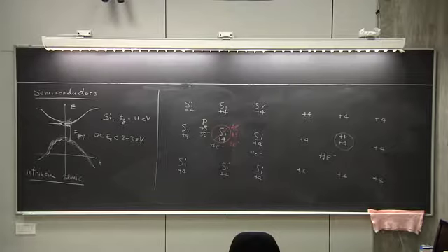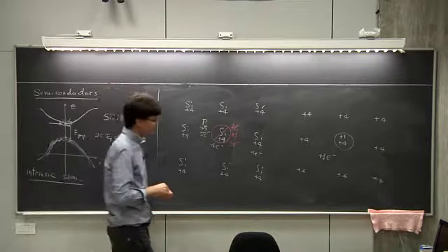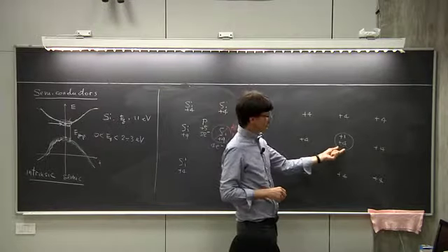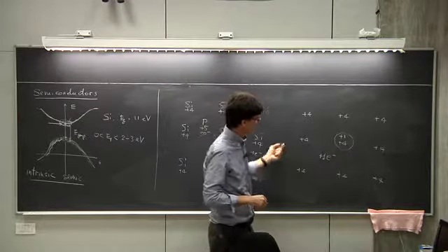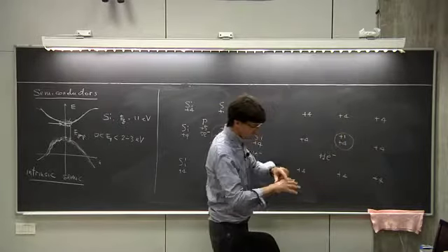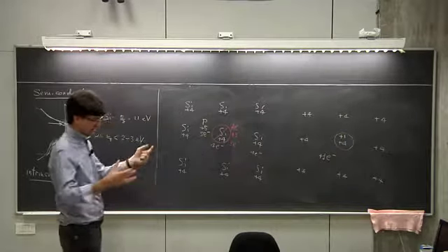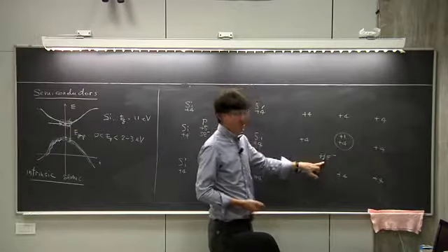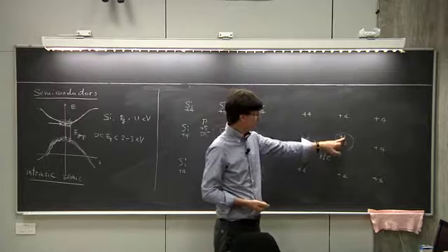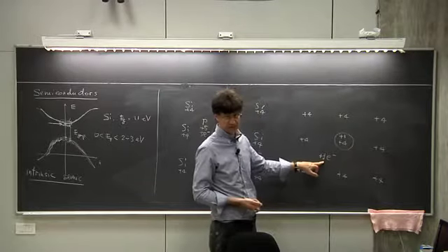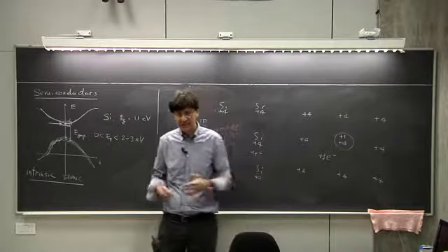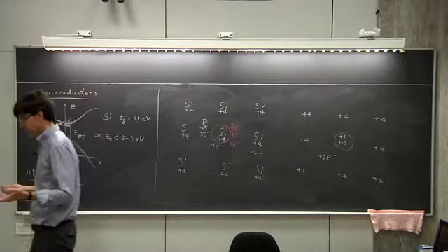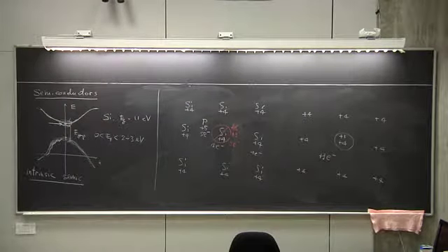In fact, without trying to go into too much detail, you can see this as a silicon band structure charge density to which you're adding a hydrogen atom, plus one nucleus and an electron, which is, however, not moving in vacuum like the standard hydrogen atom, but is moving in the presence of an existing charge density of electrons, the one given by silicon.